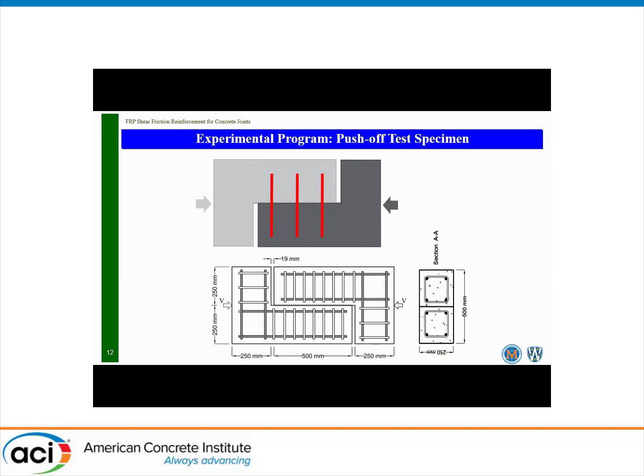We adopted different values for the contact area of the concrete to generate different reinforcement ratios, as we'll see shortly in the test parameters. Each side of the specimen was heavily reinforced to eliminate any shear or flexure cracks due to loading, with a very stiff steel plate.